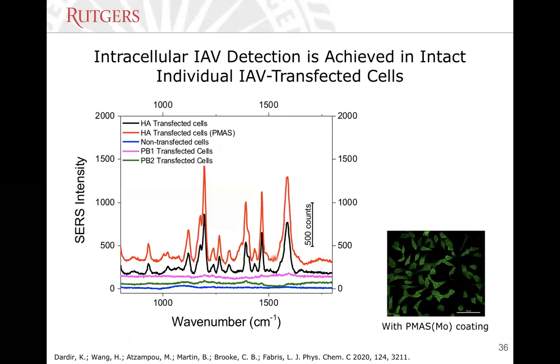The red curve represents the case where the nanoparticles were coated with this polyelectrolyte, and this polyelectrolyte is responsible for producing endosomal escape. It bursts the endosome and releases the nanoparticles into the cytosol. So we see a slight increase in the signal here. But this is extremely interesting because the cells are alive. We have loaded them with viruses and we can probe them with the nanoparticles. So going forward, we can think of not only developing devices that probe cells, but also, because these are very small concentrations, we are very hopeful that we can get a diagnostic assay coming out soon for low viral loads with diagnostic relevance.